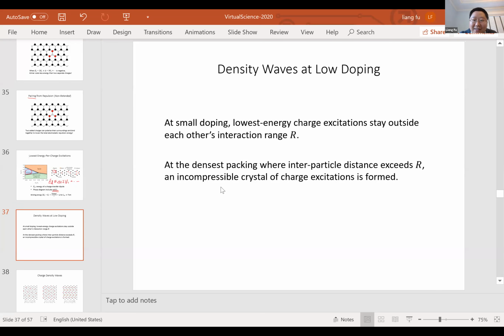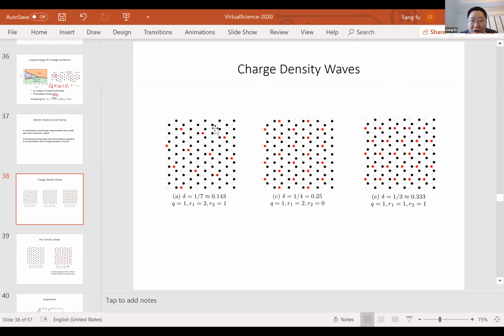But then as the filling increases, there will be a critical density that corresponds to the densest packing such that the interparticle distance is still bigger than R. We cannot go to a higher density. At an even higher density, these charge excitations now have to interact with each other, which costs more energy, right? So at this closest packing where the interparticle distance is still bigger than R, we would get an incompressible Wigner crystal of the charge excitations. If the lowest energy excitation is just a single charge, then what we get is just a triangular Wigner crystal of these individual charges. Here I've shown a few examples at 1/7 filling, at 1/4 filling, at 1/3 filling. These are essentially Wigner crystals, but they are pinned by the underlying Moiré lattice.